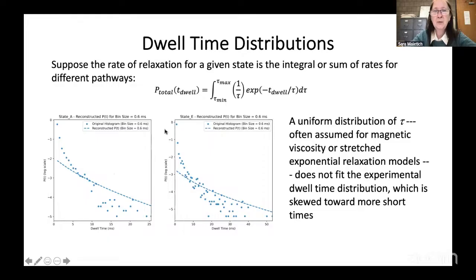What I can show you is what does not work. We do not have a uniform distribution of relaxation times between a minimum and a maximum value. If you did, you would get these dashed curves. Here's the experimental data for two different states, obviously quite different. What we can say qualitatively is that there are more short dwell times. The long dwell times are less common, but that's something that we want to understand the physics of.